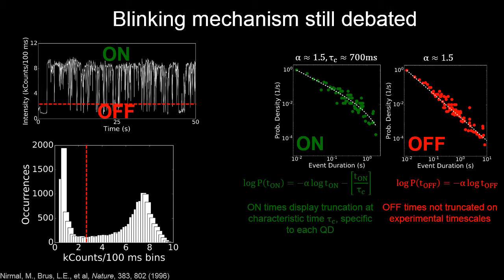Things get a little weirder when we look at the on state. We still have this power law decay, but the on state does come with an exponential truncation. The implication here is that the dots will turn off in the long time limit if I continue exposing them to the laser, which is obviously detrimental if we're using quantum dots as fluorophores.